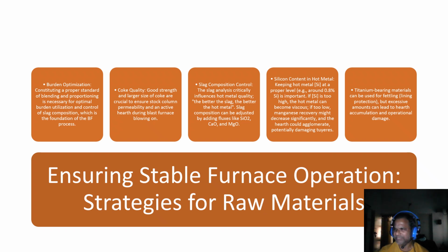Next, coke quality. Maintaining good strength and larger size of coke is absolutely essential, and this ensures the permeability of the stock column and keeps the hearth alive and active during the blast furnace blowing. Slag composition control is also one of the most vital activities. The slag analysis critically influences the hot metal quality. As the saying goes, the better the slag, the better the hot metal. Slag composition can be adjusted by adding fluxes like silica, CaO, MgO to achieve the desired properties.